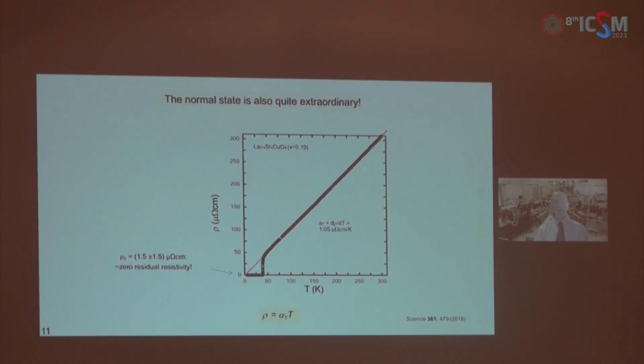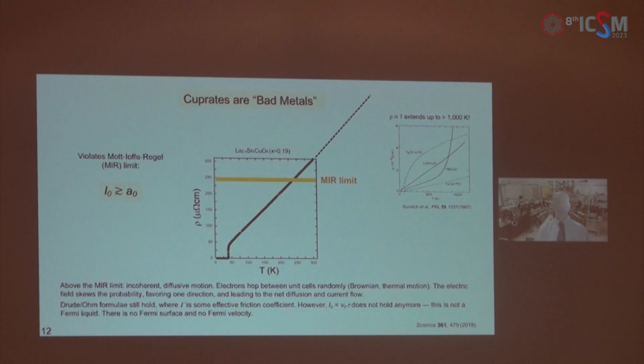And for those who synthesize samples, by this figure of merit, this is much better than any bulk strontium cuprate single crystal. Now, this temperature dependence is obviously unusual. As I mentioned, in a Fermi liquid there should be a T-squared term due to electron-electron scattering, as dictated by the Fermi statistics. Only electrons from the thermal shell, which is kT, around the Fermi surface, participate. And then there must be a T to the fifth term due to electron-hole scattering. And clearly at high enough temperature, these high power laws must overwhelm any T-linear scattering. But they do not. Neither T squared nor T to the fifth power is seen up to 1000 Kelvin.